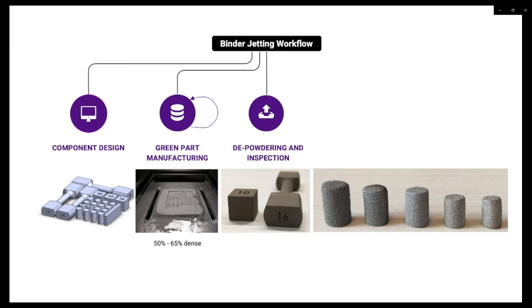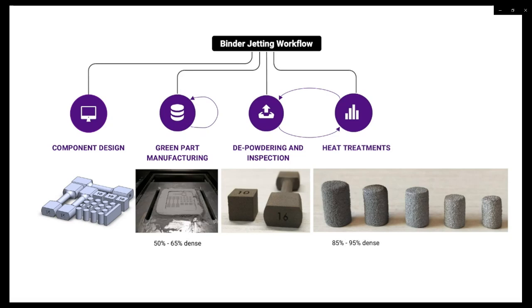The most complex part of the binder jetting process is the heat treatments. For binder jetting of metals and ceramics, heat treatments at high temperatures allow powder particles to fuse together and the material system to densify. Typical final densities range from 85 to 95%. In binder jetting, due to the heat treatment and densification process, distortion may occur. It is common that binder jetting components undergo post-processing steps, such as media blasting, machining, and infiltration. Let's take a closer look at each step.